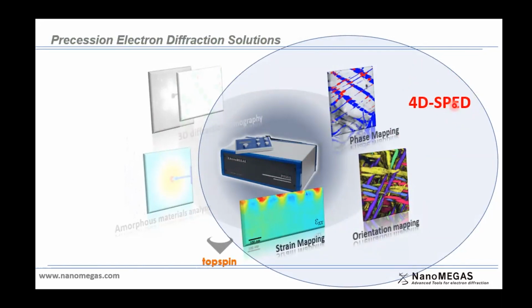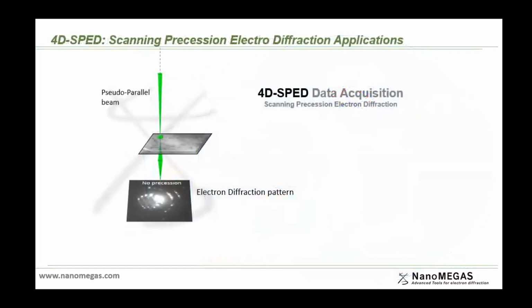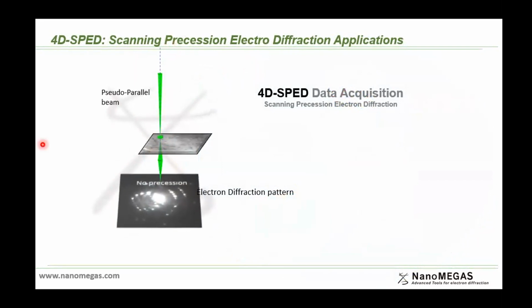So the data are acquired by this 4D SPED. And how it works, we have the beam, a pseudo-parallel beam, that goes through the sample, and then this is the diffraction pattern without precession. When you apply precession, the quality of the diffraction pattern is improved. You can see this diffraction pattern is the same as the previous one, but with precession.